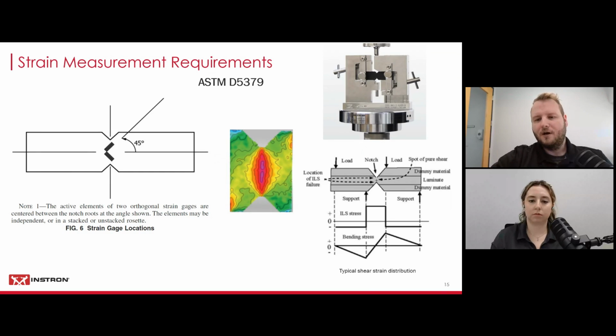This test method requires you to use at least 2 strain gauges centered in the gauge section of the specimen, which you can see here, so that V-notched section of your specimen. And these gauges need to be mounted at plus/minus 45 degrees to the loading axis. And the gauge section is a compromise based on the type of material that you're testing, because it can really influence which gauges you should use. And this testing standard actually has some recommendations on that, which are given in section 7.5.1. So that should help you to determine the right strain gauges for this kind of testing.